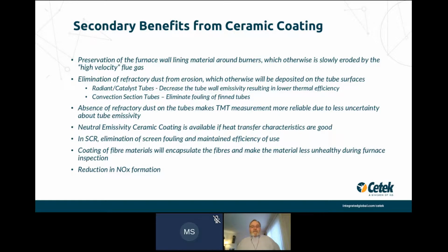The secondary benefits, I apologize, this slide's a little busy, but we can preserve the furnace lining, the ceramic fiber especially, from the hot gas abrasion, which removes the friable surface of the ceramic fiber and deposits it in the convection section or SCR units later on. It will also potentially be deposited on the radiant section tubes, which will not only insulate them to a little degree, but also make tube metal temperature measurements more difficult. So the lack of that fibery coating on the tubes will allow measurement by infrared thermography, for instance, and be much more reliable.